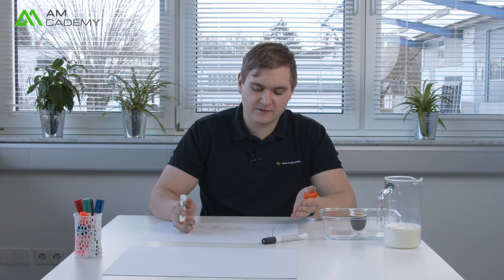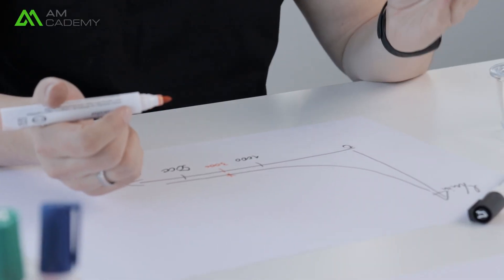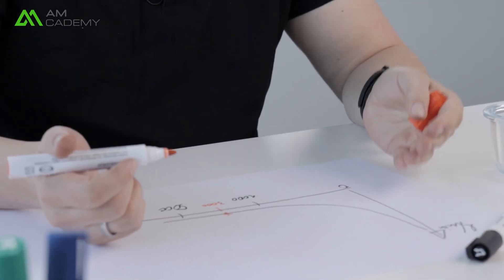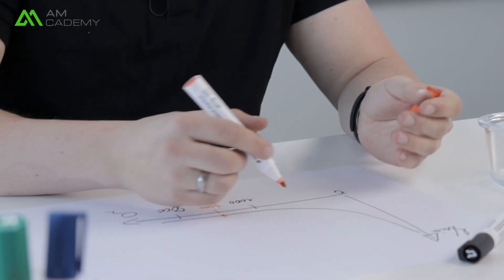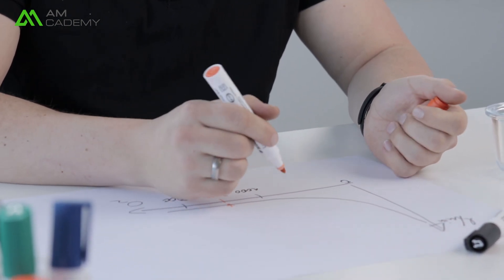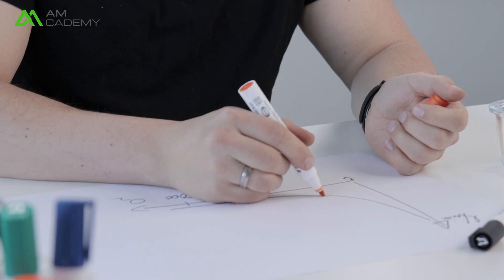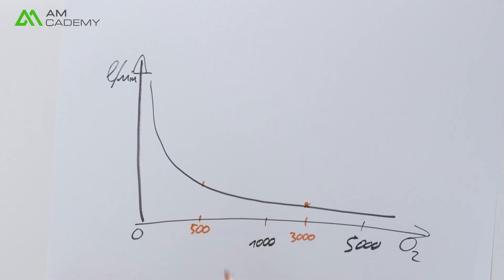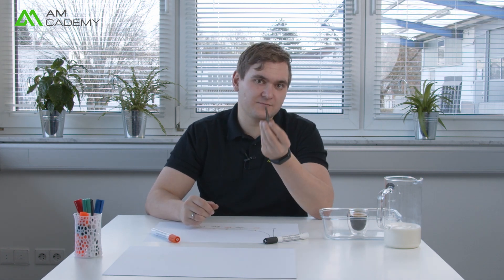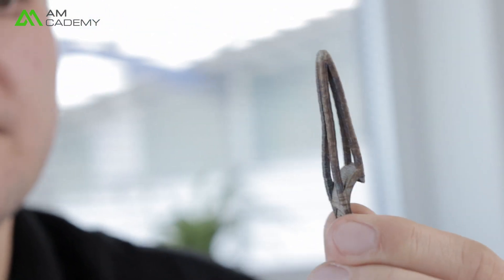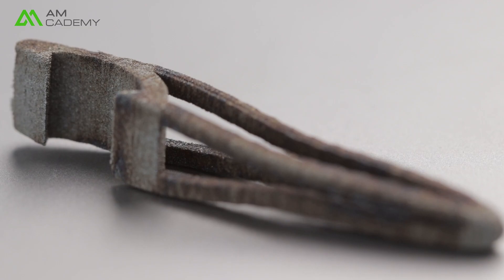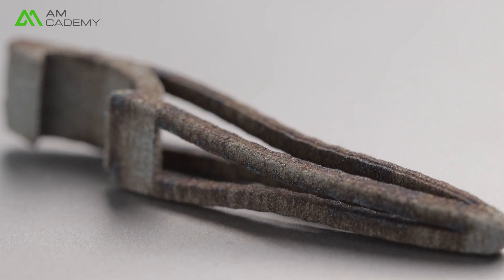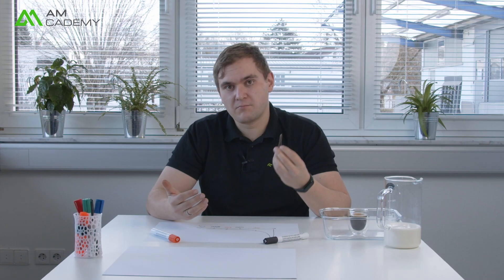Lower is always better, but lower also means you need more gas inside your machine and you have a higher cost of gas consumption. Titanium and titanium alloys are usually processed at a much lower oxygen content — typically around 500 ppm or lower, depending on the preheating of your build plate. Sometimes parts still oxidize, like this bottle opener here, and this is usually not because your shielding gas was bad or your oxygen level was too high, but simply because the part got too hot.